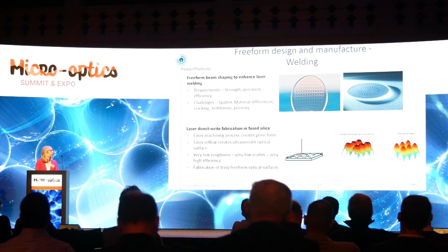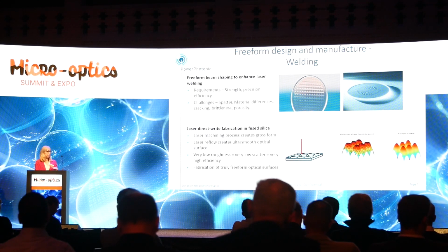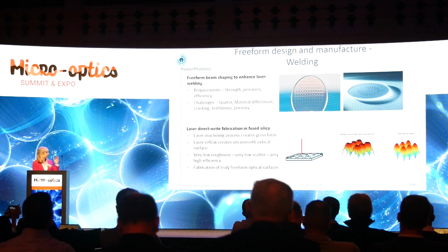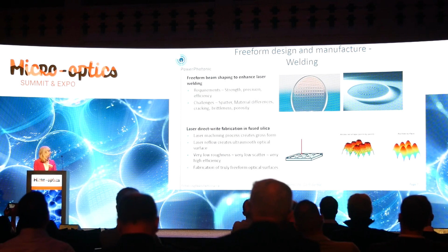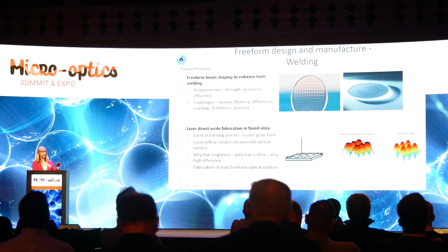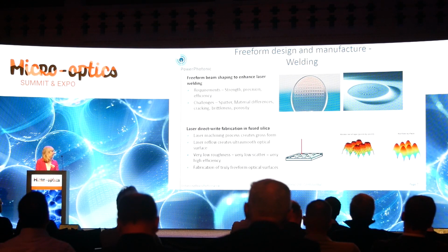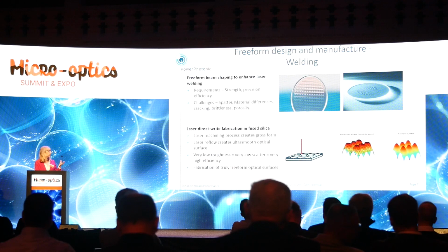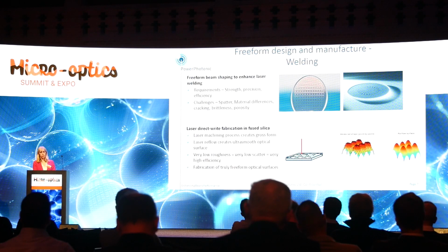The way that we manufacture our beam shaping optics to help with this is using direct fabrication using a laser also. We use a laser machining process which ablates a gross optical form on the surface of fused silica, and it's always fused silica. That ablates the net shape, you can see in that picture, point by point. Then we use the same laser to go back over and reflow the surface, so it takes it back to the bulk fused silica, and it creates an ultra smooth optical surface, which gives very low roughness, very low scatter, and really high efficiency. That means it can be used in high power welding, but also in low power welding as well. The reason we can get our different beam shapes is because the fabrication that we can do with our technique is truly freeform.